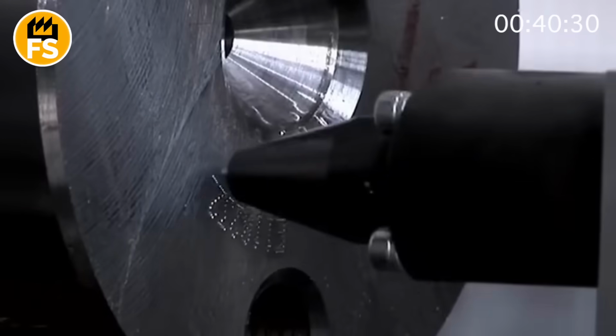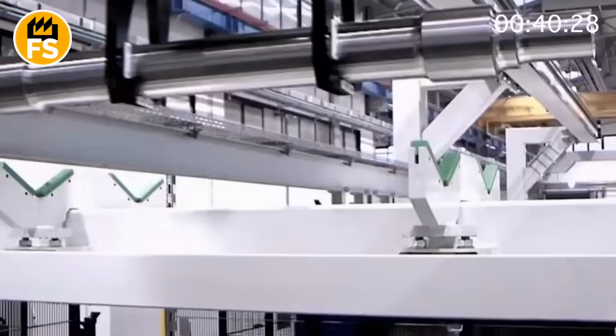At the point of contact between the wheel and the rail, the pressure reaches high values. The contact area is comparable to the size of a dime. In this area, the pressure averages 90,000 pounds per square inch, and peak values can exceed 145,000 psi. Such loads exceed the yield strength of the steel, causing plastic deformation of the metal at the point of contact with each rotation.